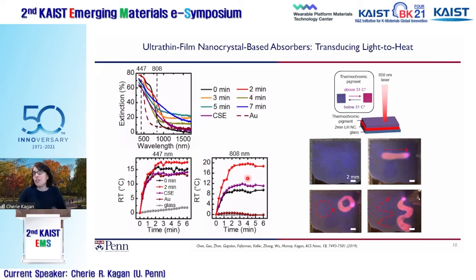For a demonstration, we layered on top of this nanocrystal film a thermochromic pigment. You can see that wherever we shine the light and generate heat at 808 nanometers in the metal film, the thermochromic polymer on top changes color in response. So there are examples where, from an application space in optics, we'd like to make strong optical absorbers. Again, using nanocrystals gives us a way to access and design very thin optical absorbers and have them operate at wavelengths that we might not have for other materials.